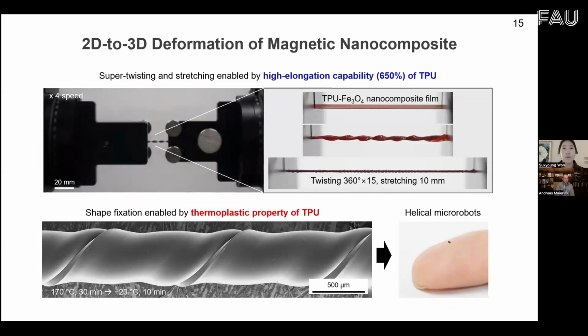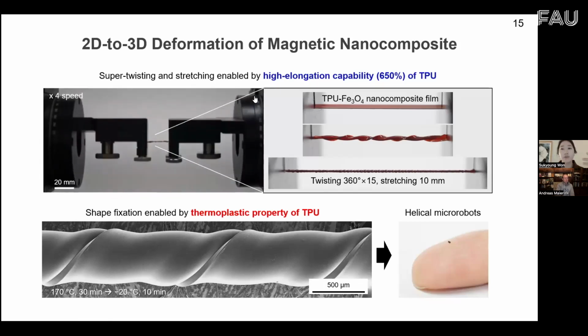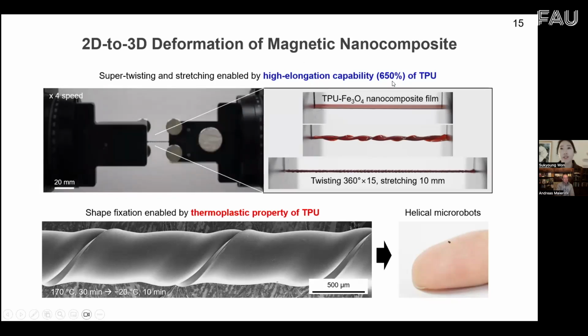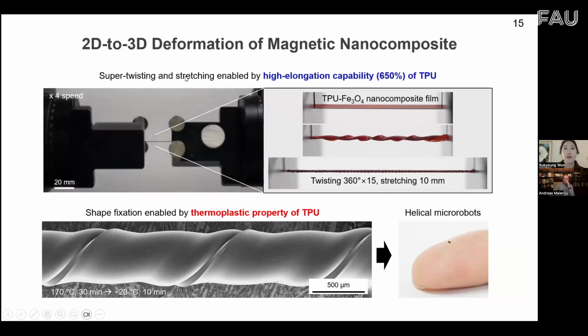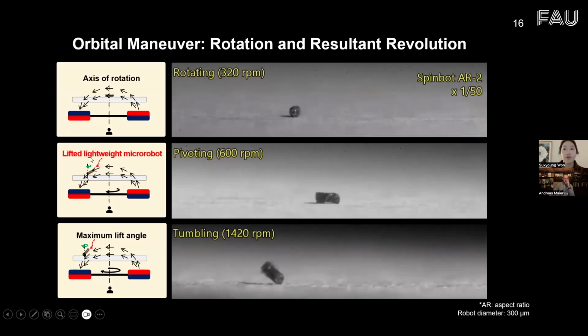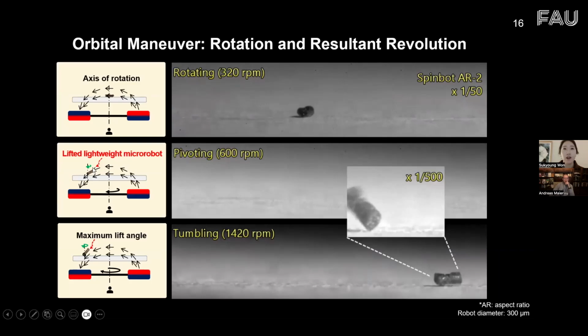And we chose the thermoplastic polyurethane matrix because of its high elongation capability of over 600 percent and its thermoplastic properties. Due to the TPU's high flexibility, we could do super twisting, stretching, and transformation of the two-dimensional nanocomposite films into three-dimensional helical microrobot structures. And also, by applying heat treatment, we could fix the shape of these helical structures after the twisting processes. Because of the lightweight nature of these nanocomposite-based robots, with a weight of only 180 micrograms, they could be easily lifted along the direction of the magnetic flux generated from the two permanent magnets.